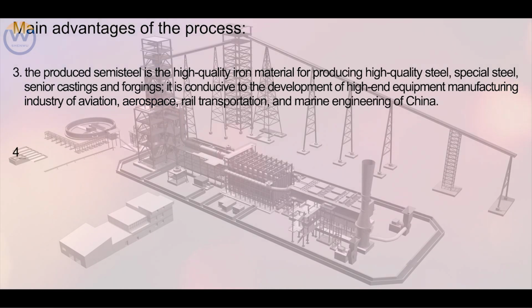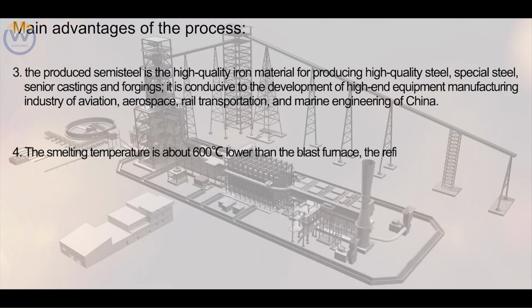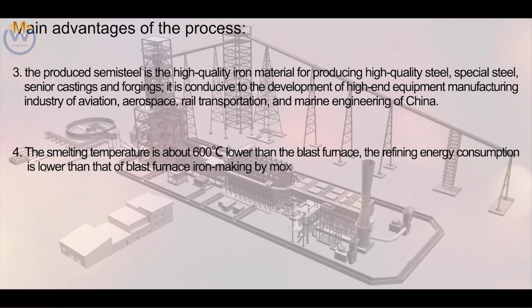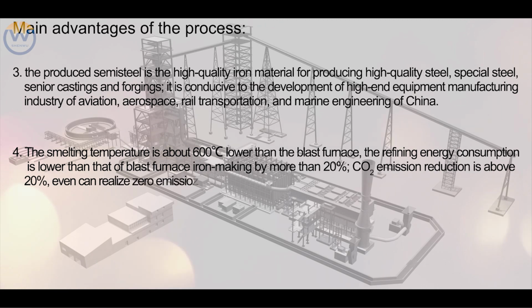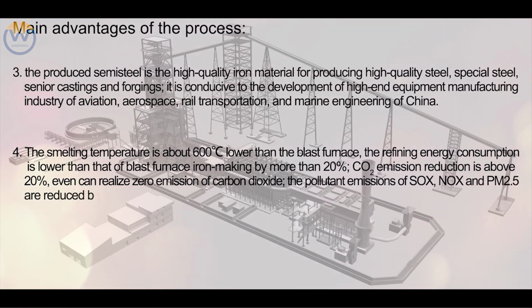4. The smelting temperature is about 600 degrees centigrade lower than the blast furnace. The refining energy consumption is lower than that of blast furnace iron making by more than 20%. Carbon dioxide emission reduction is above 20%, and it can even realize zero emission of carbon dioxide. The pollutant emissions of SOx, NOx, and PM2.5 are reduced by more than 90%.